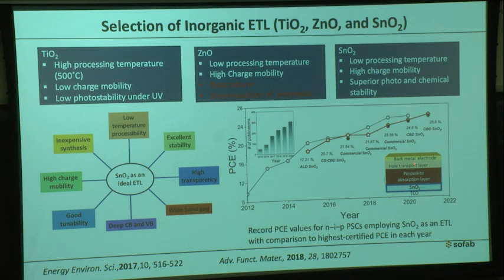Can we deposit tin oxide directly on top of the perovskite, and then provide an alternative to C60? People deposit C60 on top of the perovskite. Can we use tin oxide instead? Can we replace C60 with tin oxide? There are two fundamental problems to depositing tin oxide directly on top of the perovskite.